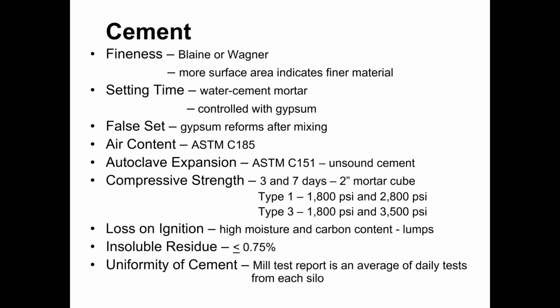There's another event that we need to be aware of, and that is a flash set. Okay, a flash set is a rapid hardening of the concrete that results from the reaction between the cement and the water. So flash set is a real set, and if that occurs while the concrete is in the mixer, then we need to act quickly to start getting the concrete out of the mixer. No matter where the concrete is at, if we get a flash set, we need to act quickly to get the concrete out of that container. Otherwise, we're going to have to spend a lot of time with jackhammers getting the concrete out. So flash set is a real set of the concrete. It's not reversible, and we cannot use that concrete. That concrete has to be discarded.